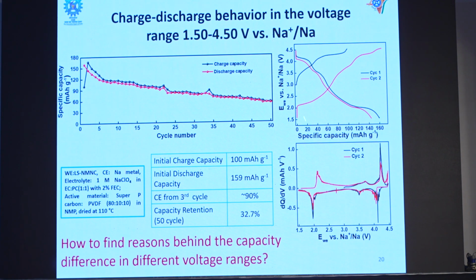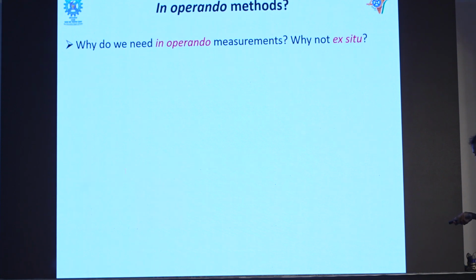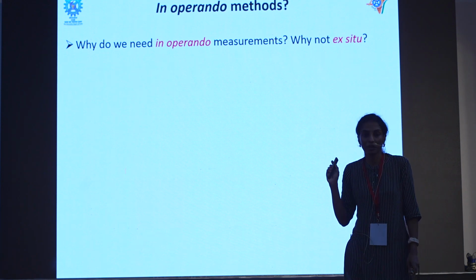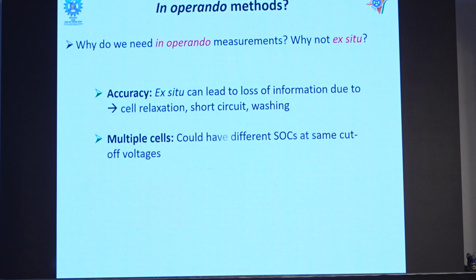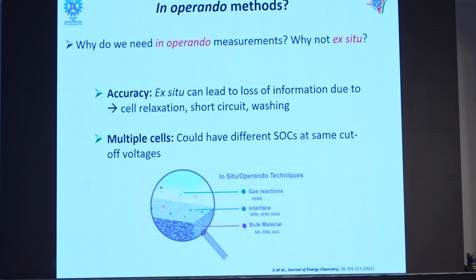So we have increased the operation voltage to 4.5. And at 4.5 volt, our capacity degradation was much higher, which is normal because your electrolyte will decompose at this particular voltage. And now to understand the reason behind it, we went to do in-operando methods. Why we do in-operando methods is, if we are doing ex situ, that means we open the cell and measure it separately, we can end up with a loss of accuracy because the cell can undergo short circuit or cell relaxation. And we have to do multiple cells in order to get any information, and if we do multiple cells, we end up with multiple results. That is another problem. That is why we wanted to do it while the cell is operating.